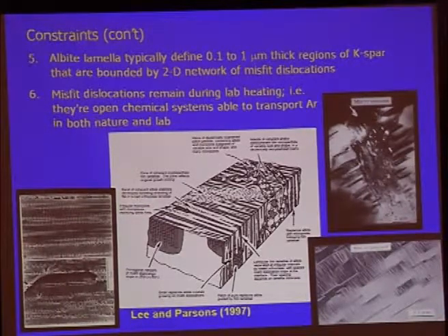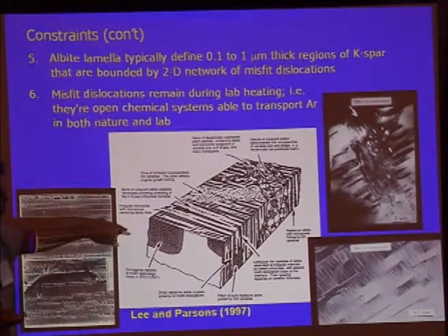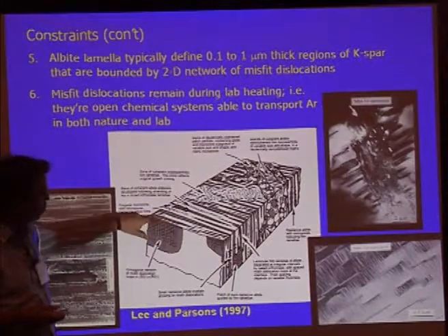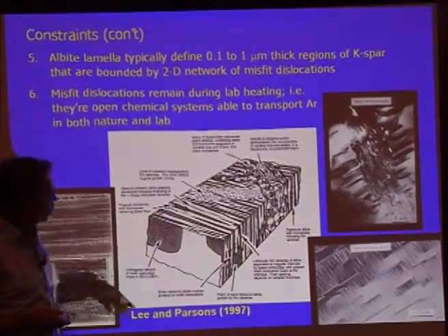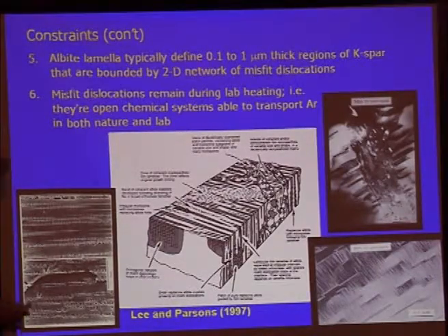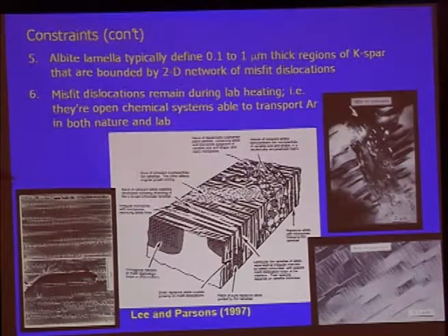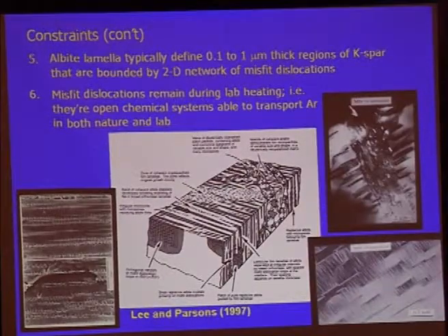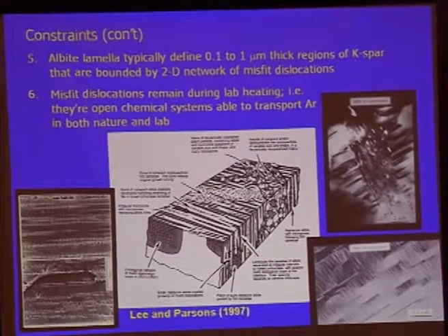you're going to, in fact, in the regions that have any appreciable sodium in, you're going to exsolve out albite perthite lamella. Okay? And what's fascinating, actually, is when these lamella form, at the very smallest scale, there's essentially just the difference between the unit cell of a potassium feldspar and an albite, an orthoclase and an albite. Say the orthoclase unit cell looks like this, and the albite unit cell looks like this. Well, that's an exaggeration, but something's got to give.